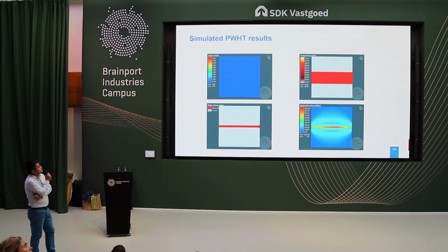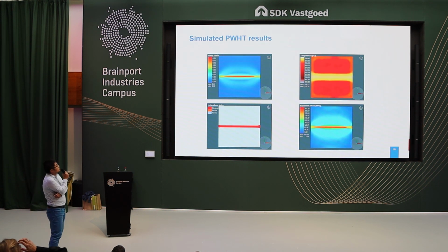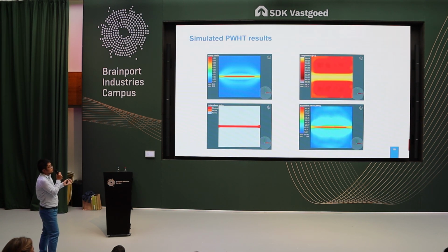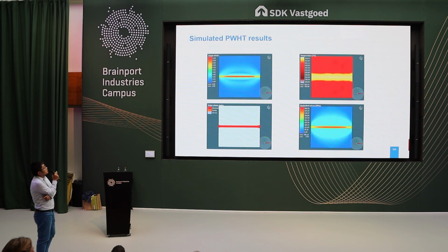And we can also, based on the welding model, do some post-weld heat treatment simulation. In the first image, you can see that we first translate the welding-induced result to this model. Then we also include the creeping effect. Therefore, the residual stress from the welding will transform into the creep strain. And for this, the second image shows the temperature evolution.